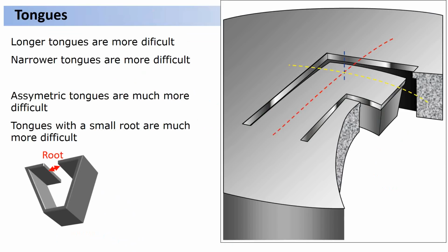So the things we have to realize is that the longer the tongue, the more difficult the extrusion. The narrower the tongue makes it extremely difficult because once again, we can't get support up in there to satisfy the requirements for this 98,000 pounds per square inch. As we start to introduce cantilevered tongues, then not only do we get the direct caving in the extrusion direction, but we also tend to get twisting, which, as you can tell, the more you twist and bend, it's going to want to break quicker. So the idea is to try and keep the root of the tongue as wide as possible so that the depth does not get caught up and break the die itself.